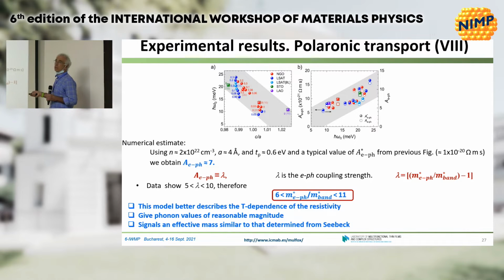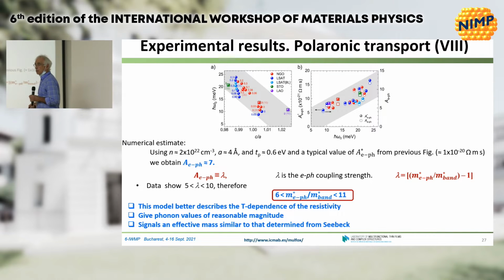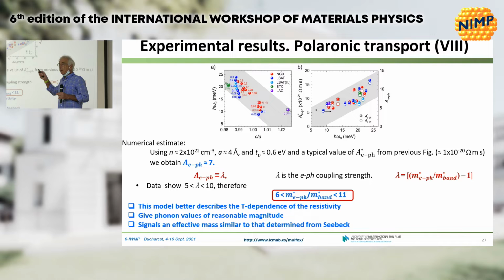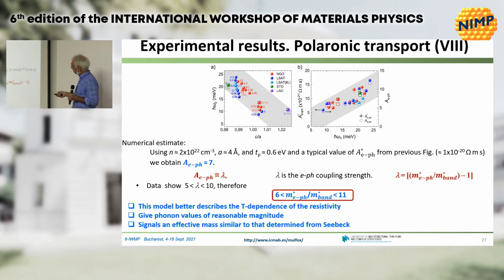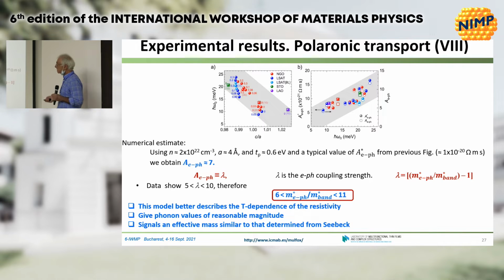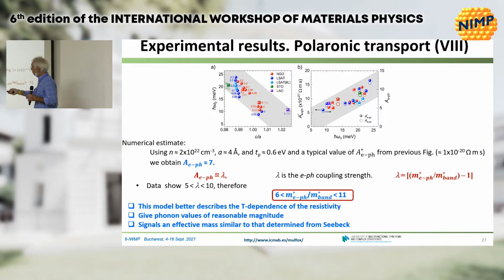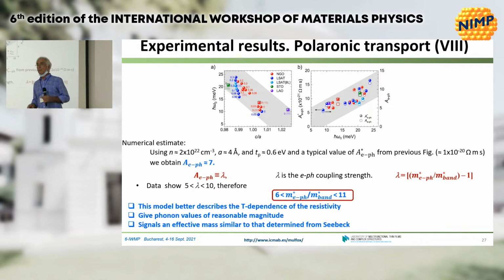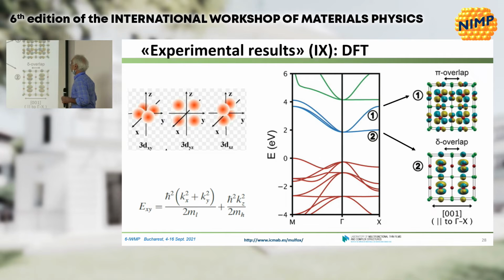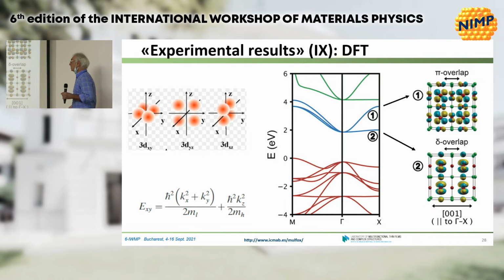This is the electron-phonon coupling parameter in these oxides, which is about 7, something similar to what was extracted from the spectroscopic data that I showed you before. The effective mass is going to be very large, associated to this electron-phonon coupling, and from this plot you extract an effective mass between 6 and 7, depending on c/a, which is quite comparable to the previous data.